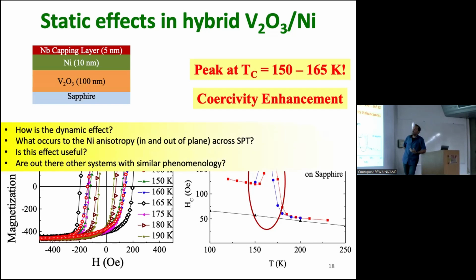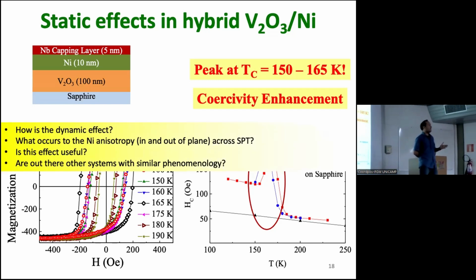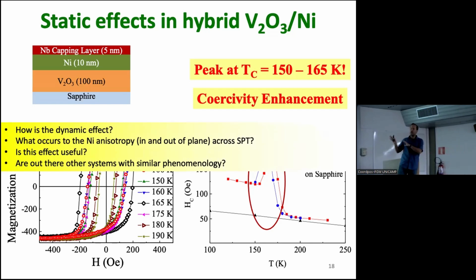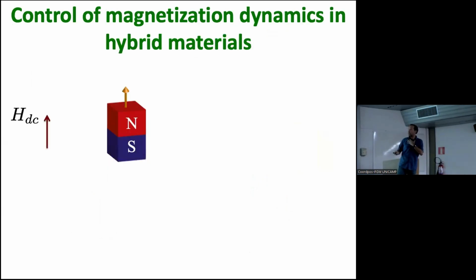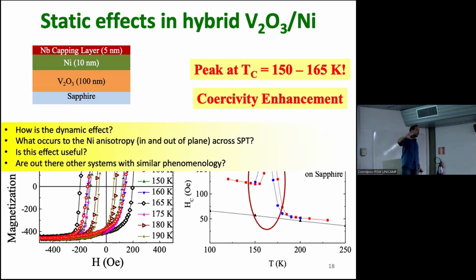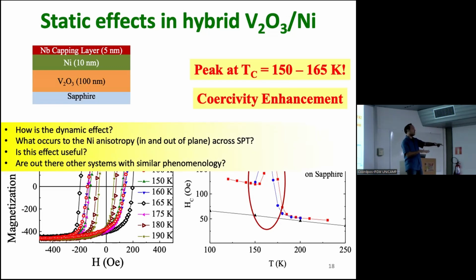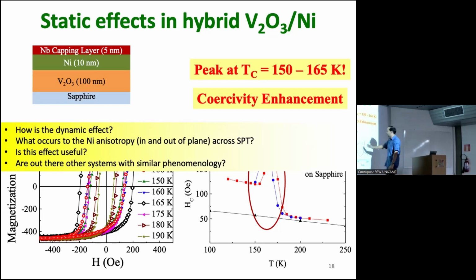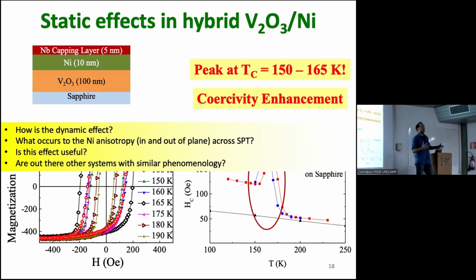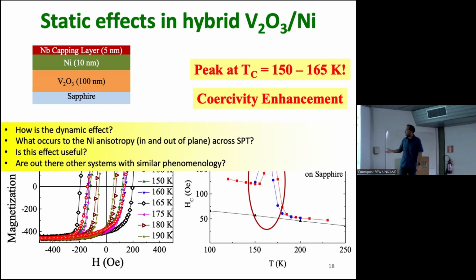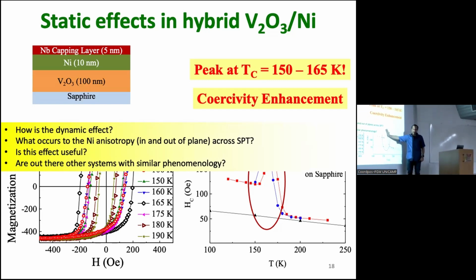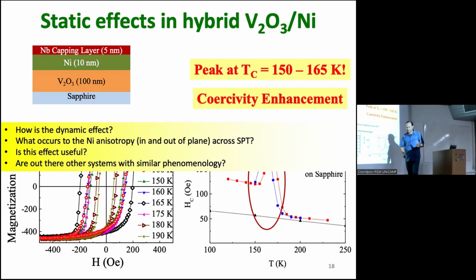But anyway, the idea is that we can control the static magnetization just by changing something. So what's going on here? We tried to explain it. We did some micromagnetic simulations, basically to simulate what will happen when you break into domains due to the strain of the vanadium oxide. Because you have different domains, different crystal structures, every structure will change the nickel in a different way. Then you have a gradient of strains. And just in the interface is where you actually have the most stress, because you have a bunch of interfaces. And that is exactly why it's higher in the middle of the transition, and then it's different at higher or lower temperature. That's kind of the main idea.